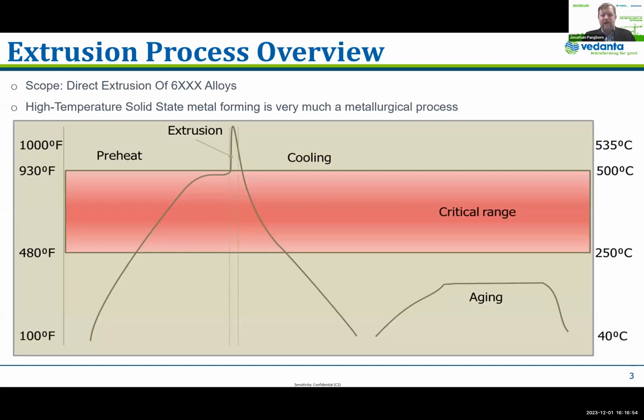So here is an overview of the extrusion process. Many of you have probably seen this before. But we see here in the extrusion process, the main steps of preheating, extrusion, cooling, and the aging process, and having respect for the critical range where magnesium and silicon grow undesirable particles. Because really, and I should point out, this is the scope of direct extrusion of 6,000 alloys. Other alloys are going to behave differently. For example, some of you are using 3,000 alloys, but a lot of these quality aspects are still going to apply.